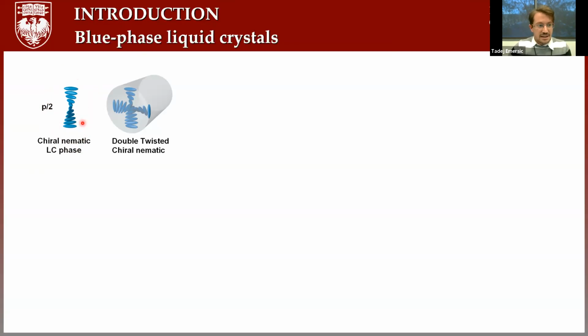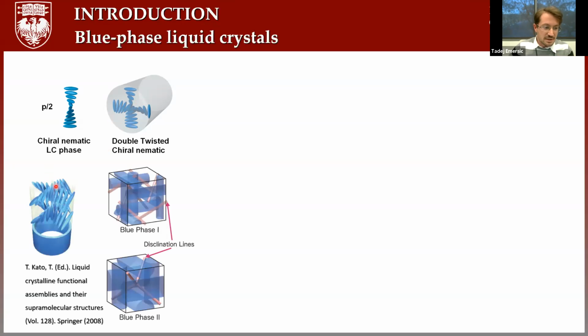And in case the chirality in this system is very high, or in other words, the pitch is very low, then at some certain temperature, the system spontaneously goes into a double twisted chiral nematic, as we can see here. So here we have twisting in two different directions that are perpendicular to each other. And this then forms these double twisted cylinders, as we can see here.